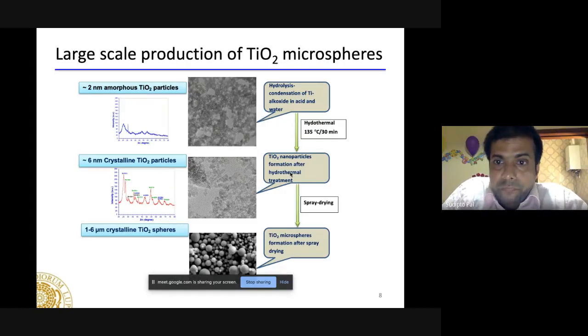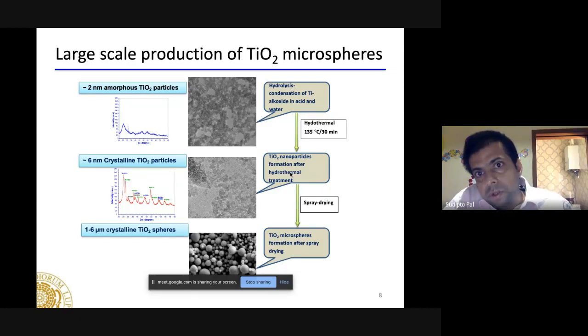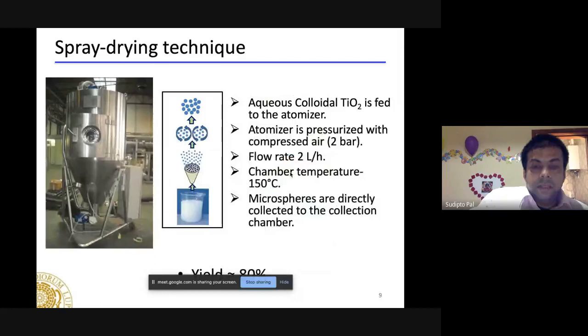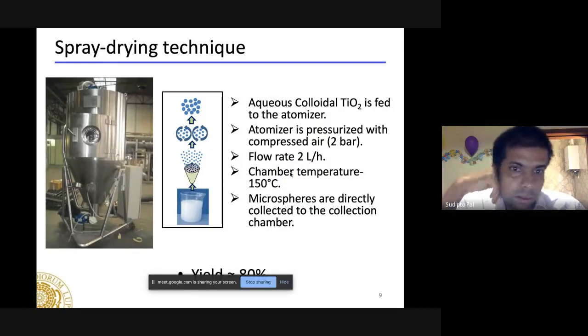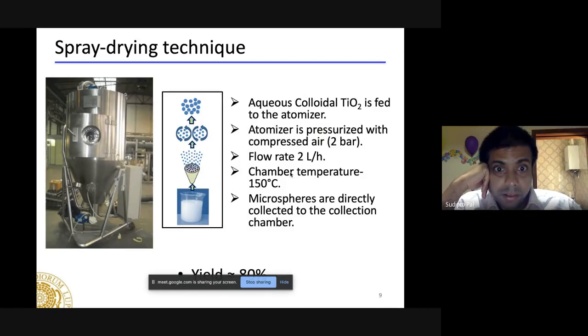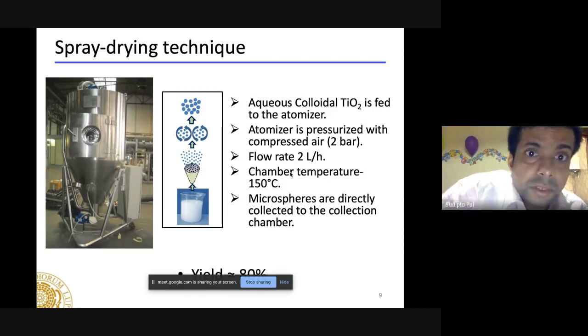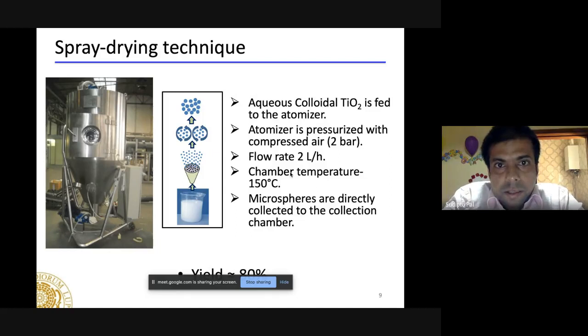But one major problem is to produce these nanomaterials. But in our laboratory, we have produced this material on a large scale, mainly industrial scale, by one method. It's called hydrothermal and spray drying. So what we do, we take one precursor of TiO2 and make it soluble in water, and with hydrothermal treatment, it can be converted from amorphous to crystalline, and then we spray dry it. So what is spray drying? This is the setup of spray drying, where at the bottom the TiO2 sol is left, and then it is sprayed with one atomizer, and with the air pressure it forms droplets, and it forms spherical spheres.